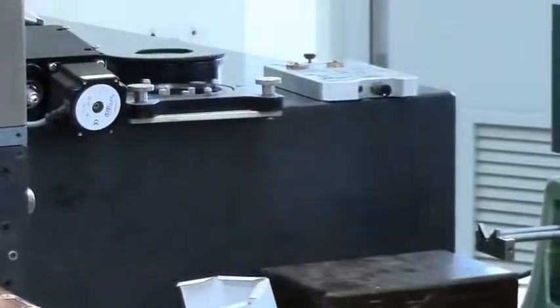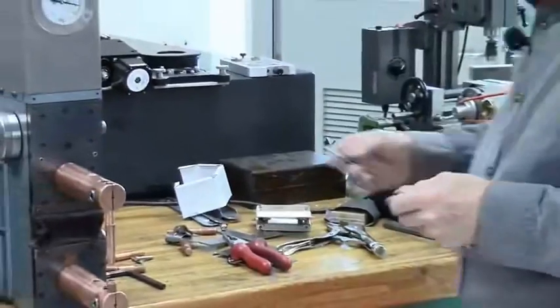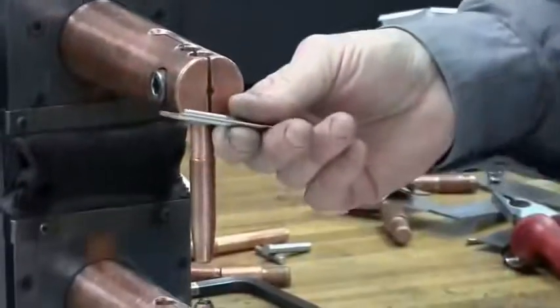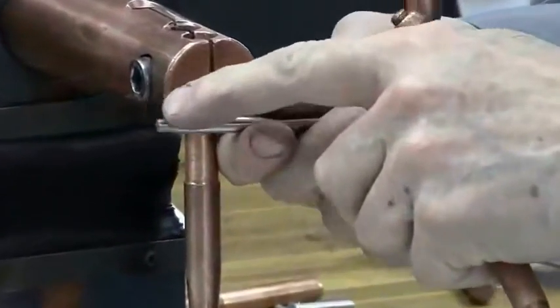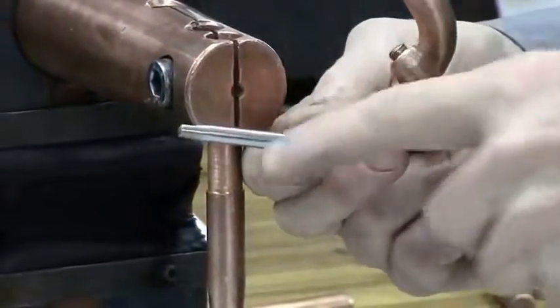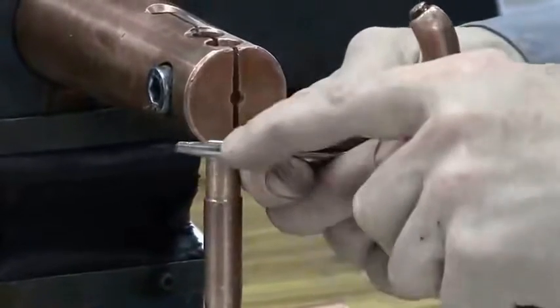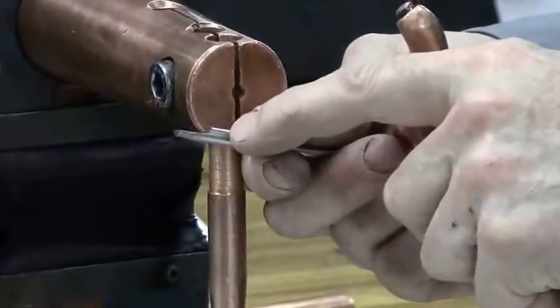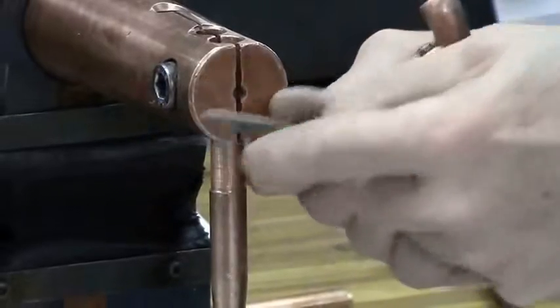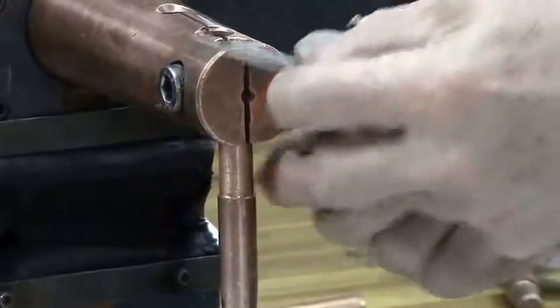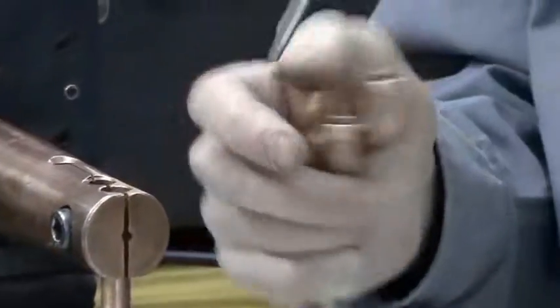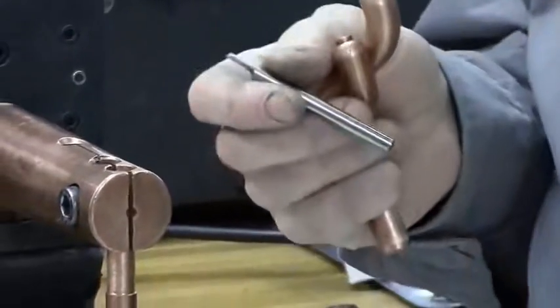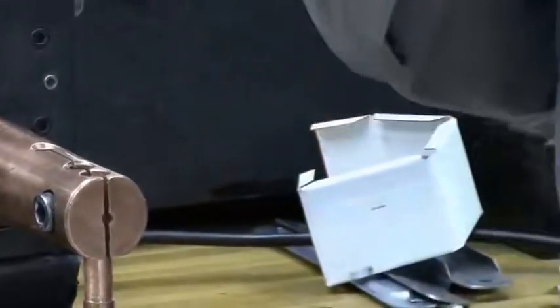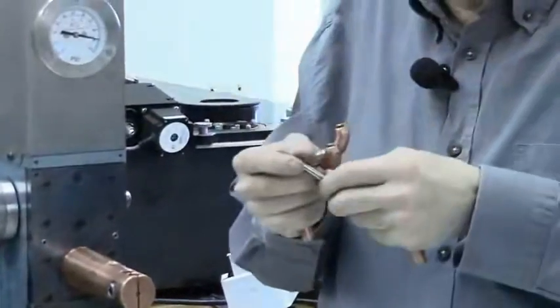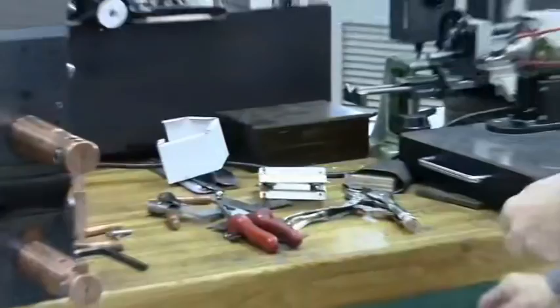To make the taper hole, you just take a dowel pin, grind it, taper, freehand. It doesn't have to be accurate. Just put it in a drill against the sander, make it taper. Grind it flat to half the diameter. That's called a D-bit, and that's a milling cutter basically. So that's how you make yourself milling cutters, and that is hard enough to cut copper. With this you drill the taper hole, and then you machine a taper on the insert and press it in. It doesn't have to be accurate because the copper will flow. So you just squeeze hard, it will make it on shape. So that's how you put the tips in.